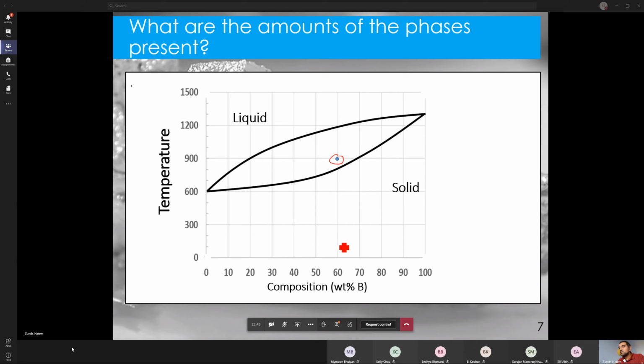Whereas if I look at the next example we have here, if I take this point instead, so if I gave you a different alloy and said, why don't we put 60% B and 40% A, and hold at 900 degrees. So we're interested in this blue point over here. We know again that we will have solid plus liquid because we are in this middle region. Interestingly, the composition of the liquid has not changed, it's 20%. The composition of the solid has not changed, it's 70%. And I got those just by drawing a horizontal line here.